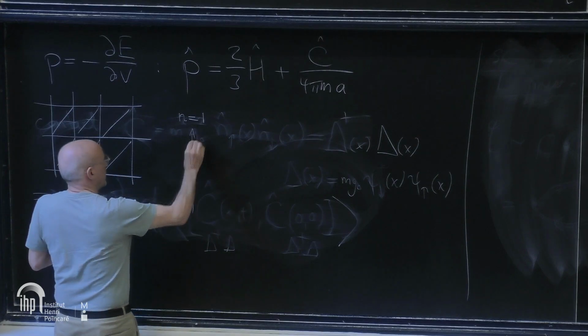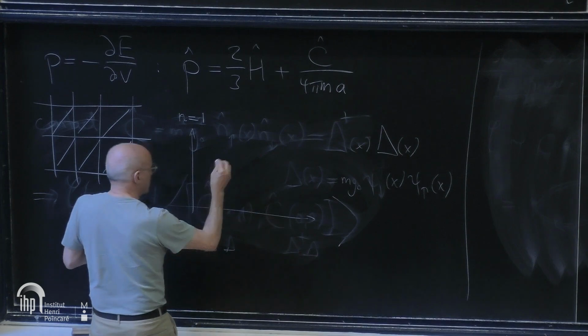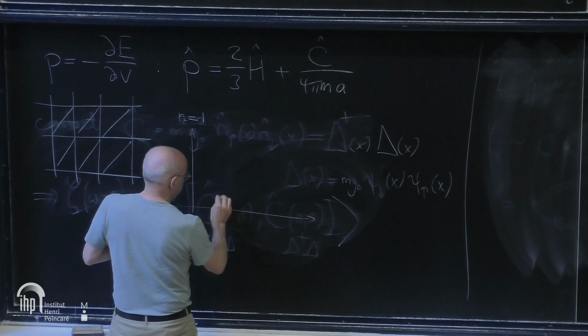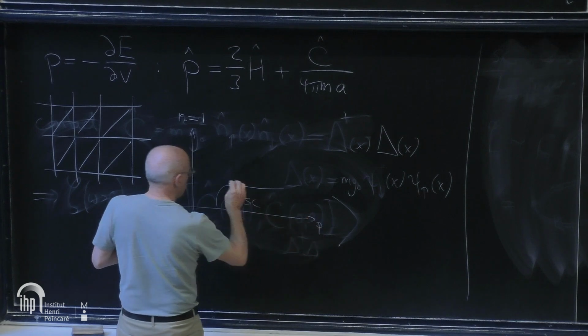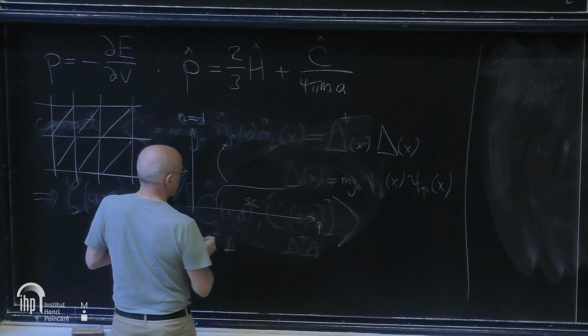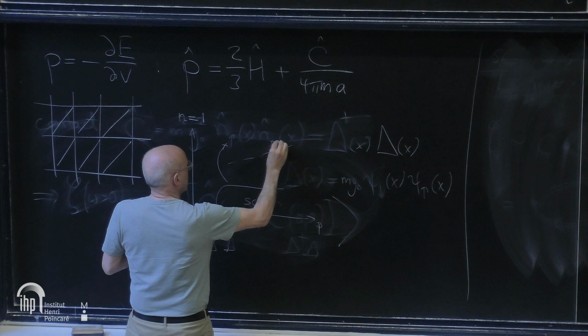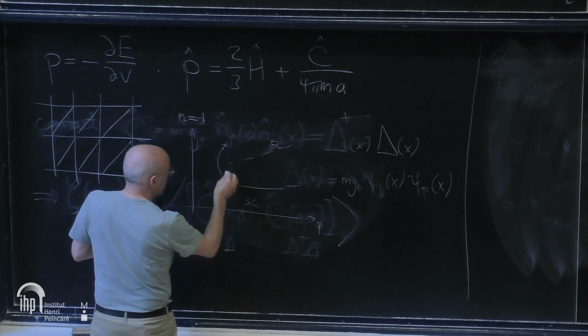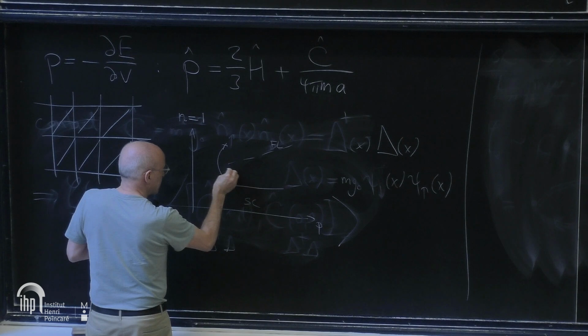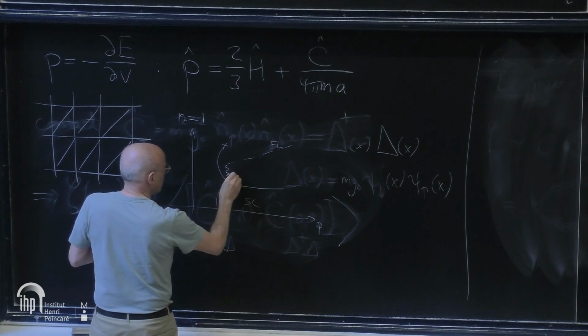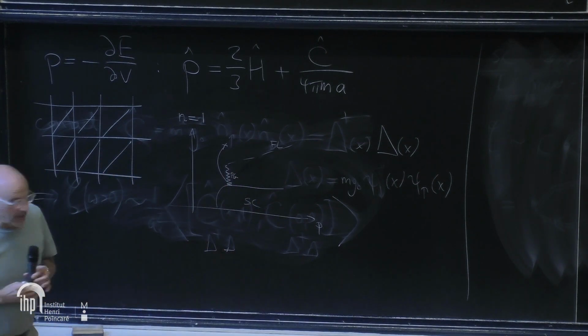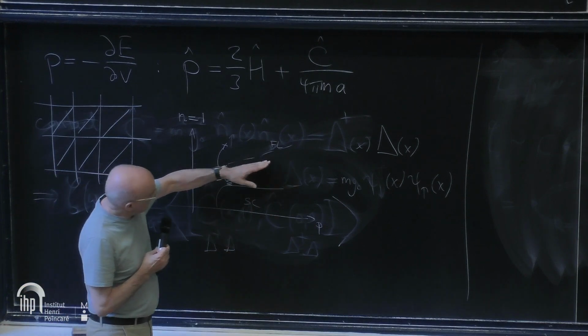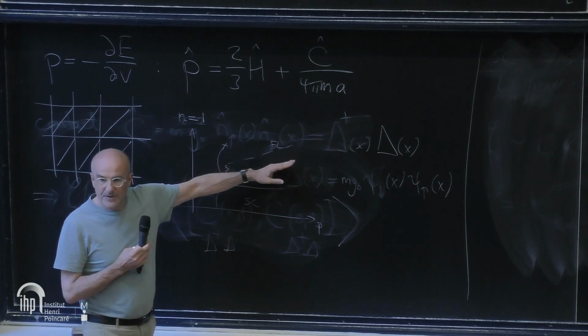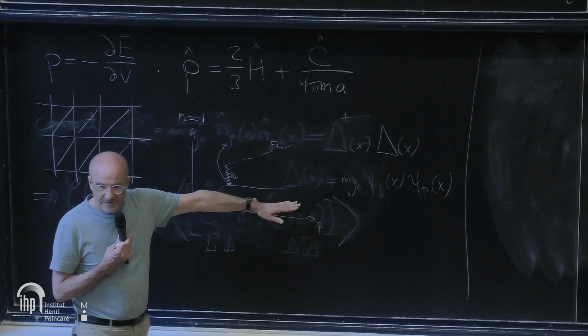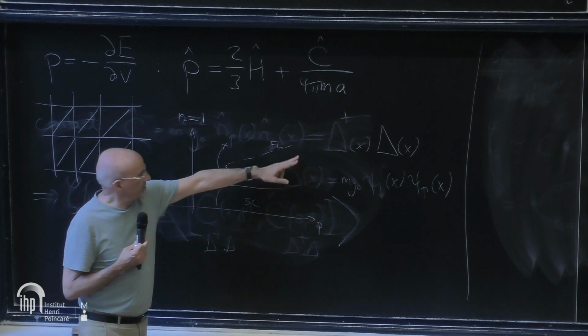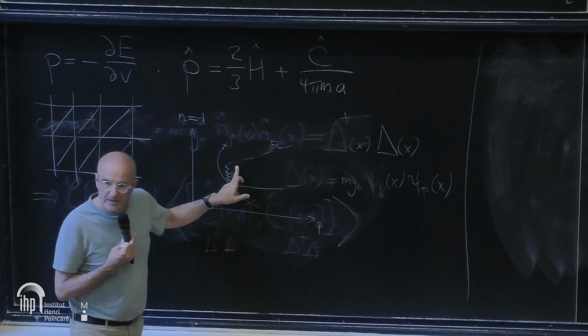Again, I don't want to claim that there is no pseudogap physics in this system, but what experiments are telling you is that there is a superconducting phase. This is pressure. This is a metal insulator transition. There is a Fermi liquid coherence scale. And perhaps here, very close to the metal insulator transition, there is a small region of pseudogap. But perhaps the most striking thing is that these materials do not have the strange metal regime of the cuprates. Below this scale, the resistivity is T square.